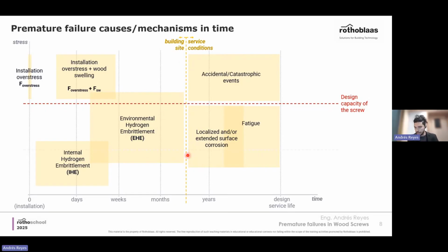After the building site is closed, and this is very important, both internal and environmental hydrogen embrittlement, at least this is what the literature states, can be excluded. Most cases can be excluded. I would say maybe just a little bit after the building site is closed, because they depend on the conditions that need to be present. In the case of environmental hydrogen embrittlement, corrosion, for example, is a very relevant condition. And when the building site is closed, exposure to moisture generally is stopped. So in that case, we could stop talking about environmental hydrogen embrittlement.